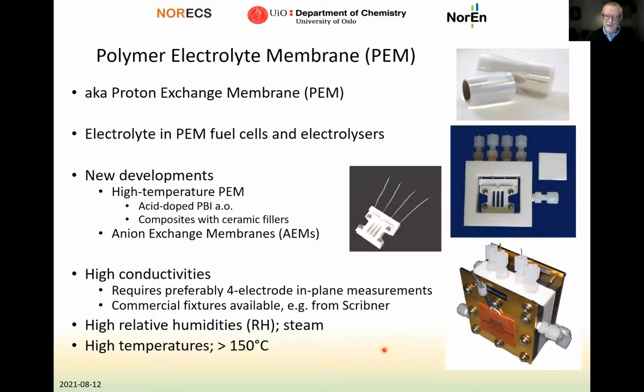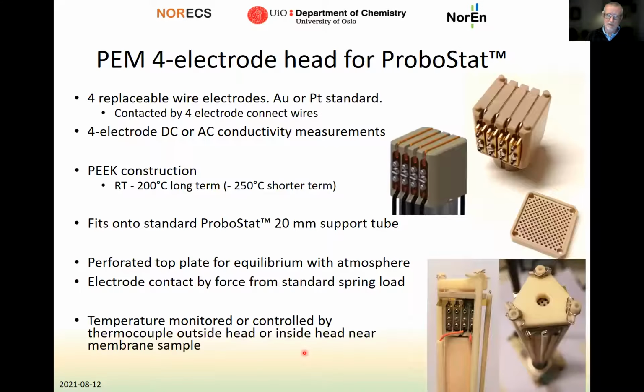This allows you to supply controlled humidities, high relative humidities, meaning steam at high temperatures. And you can also heat these up to elevated temperatures, like typically up to 150 degrees. So these work well and are well established for testing PEM membranes. And now we have also developed this 4-electrode head for the ProboStat, for those who have a ProboStat.